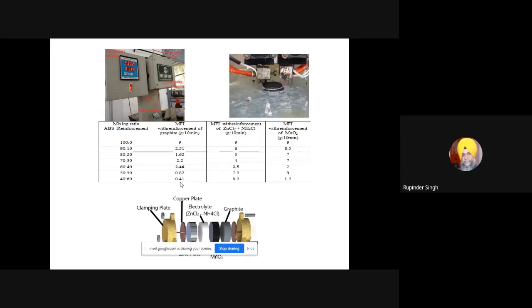This is just the reverse of the viscosity of the material, basically to understand how many grams per 10 minutes my material is flowing. So we repeated this exercise with the reinforcement of graphite, then with zinc chloride and ammonium chloride, and similarly with MnO2, and we tried to see at which particular proportion I am getting an MFI in an acceptable range. You can see over here the 60-40 ratio for graphite is giving me a value in the range of 2.5. Similarly for zinc chloride and ammonium chloride, again in a similar range. And for MnO2, this may be in the range of 55-45.